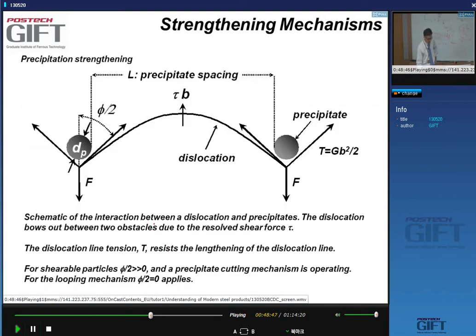All right. So the theory, again, is available. We won't go into the details of the derivation of this theory. But if you're wondering why the square root is in the denominator in one case and the other one not, it's basically due to the fact that when you have these shearable particles, you have a very much larger angle phi over 2. So it's much easier for the dislocation to move through the particle.